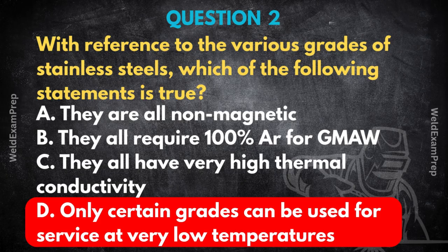Now, why is D correct? Only certain grades can be used for service at very low temperatures. Right. This is super important, especially for industries dealing with cryogenic temperatures, think LNG, liquid nitrogen, that sort of thing. Very low temps. Extremely low. Now, many materials get brittle, dangerously brittle, when they get that cold. But austenitic stainless steels, again, thanks to their stable crystal structure, generally keep their ductility and toughness even at cryogenic temperatures. Oh, good for that. They're often ideal for things like LNG tanks or cryogenic piping.